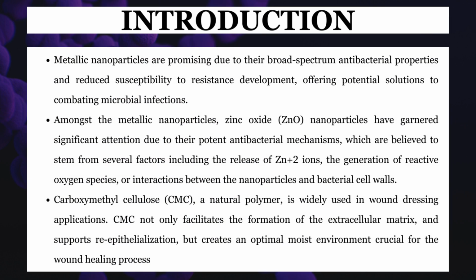Metallic nanoparticles are promising due to their broad-spectrum antibacterial properties and reduced susceptibility to resistance development, offering potential solutions to combating microbial infections. Amongst the metallic nanoparticles, zinc oxide, ZnO, nanoparticles have garnered significant attention due to their potent antibacterial mechanisms, which are believed to stem from several factors, including the release of Zn2+ ions, the generation of reactive oxygen species, or interactions between the nanoparticles and bacterial cell walls.